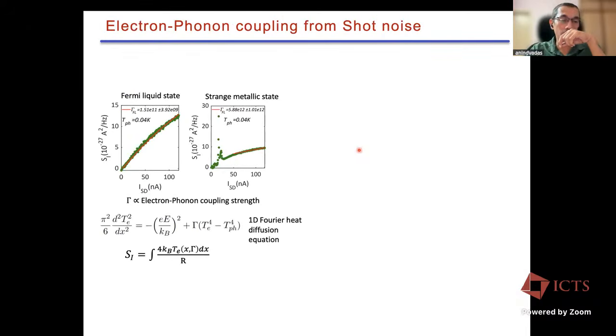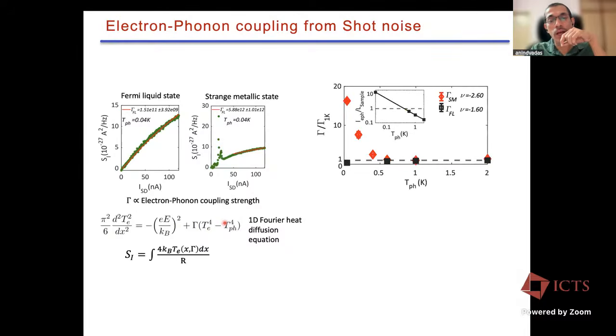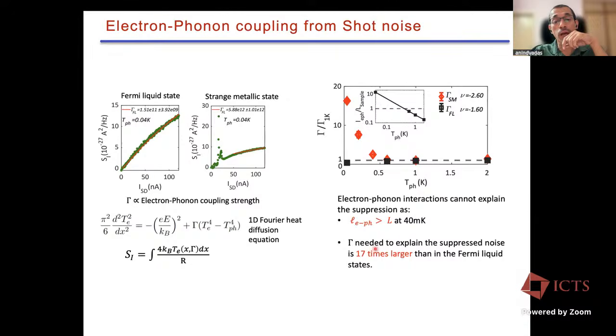We did exactly the similar analysis like the previous speaker mentioned. Of course, this is a 2D system we have used. So we have used this T square, the T to the power 4, this model. And it turns out, if you want to explain the suppressed Fano in the normal state above the critical current in the superconducting regime, you need the gamma. In this case, the gamma is just proportional to electron phonon strength. Also, it involves some other parameters. It turns out in the same system, to explain the suppressed noise, you need at least orders of magnitude larger gamma compared to the Fermi liquid regime. So that probably tells us that it is probably a strange metal.